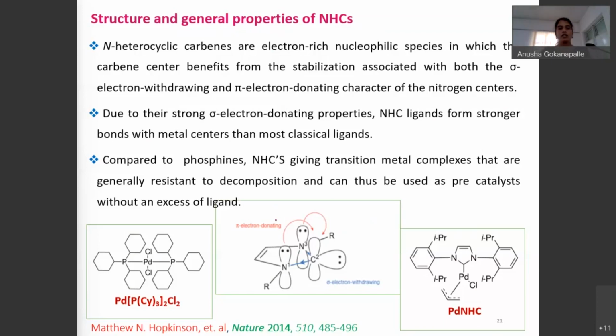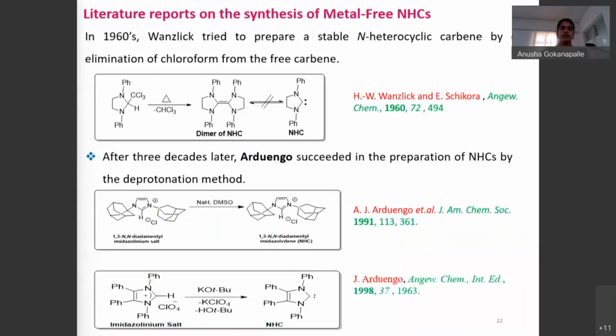Due to their sigma electron donating property, NHC ligands form stronger bonds with metal centers than most classical ligands. Compared to phosphine, NHCs give transition metal complexes that are generally resistant to decomposition and can thus be used as a pre-catalyst without excess ligand. This is the NHC, and this is the palladium NHC, and this is the phosphine palladium type of catalyst.